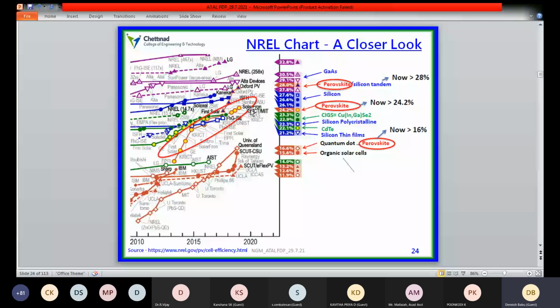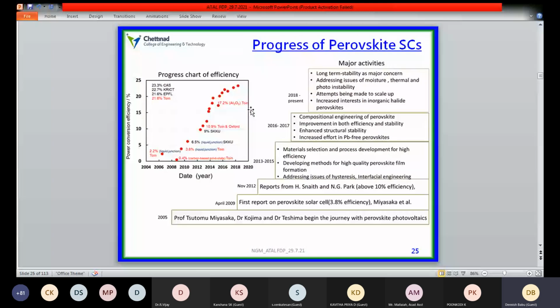In 2009, they reported the first perovskite solar cell with an efficiency of 3.8%. After that, people started to work on this material, and they have almost reached 24.2 percent. In each era, people have looked at different aspects, addressing the issues of hysteresis, interfacial engineering, and material selection for high efficiency, because high efficiency is an expected one for these solar cell materials.